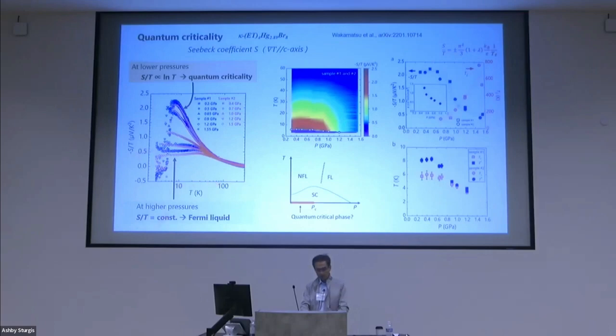In a conventional metal, S over T is constant, and in the high temperature region, just conventional metal behavior is observed. However, in the hotspot regions, S over T keeps increasing on cooling, and this straight line corresponds to the logarithmic temperature dependence. So the logarithmic temperature dependence of S over T is an indication of quantum criticality. And look at this data, it is nearly converging.